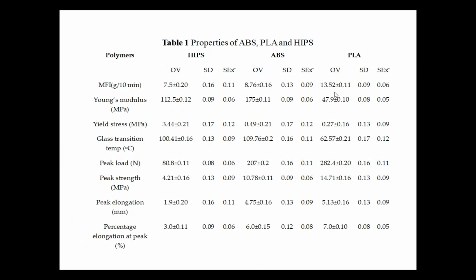Then there is a lot of difference in their Young's modulus. You can see for HIPS it was 112, for ABS it is 175, and for PLA it was 47.9. Then there is a difference in the yield stress, right? Then there is a difference in the glass transition temperature. You see 100, here is 109, here is 62. Then you can see the difference in the peak strength. For HIPS it was 4.2, for ABS it was 10.78, and for PLA it was 14.7. Then other properties like peak elongation, there was a difference, right?